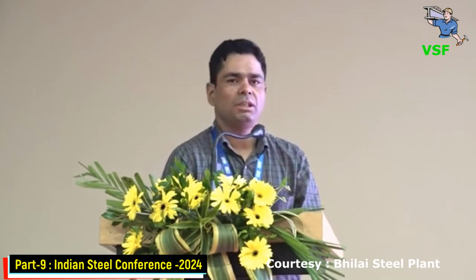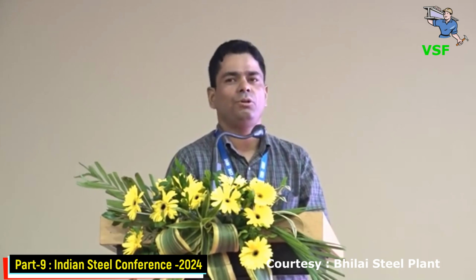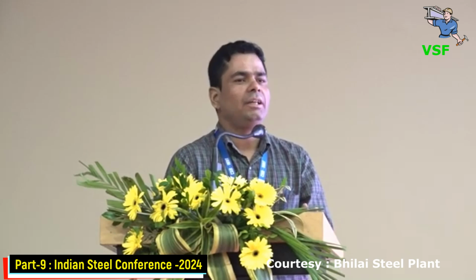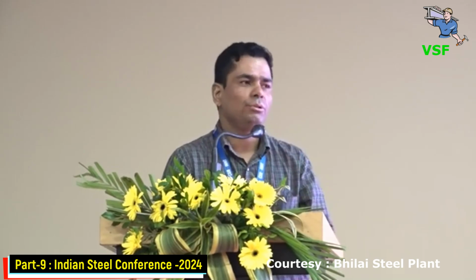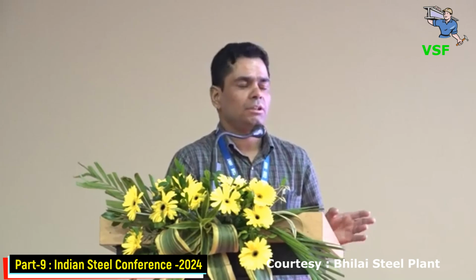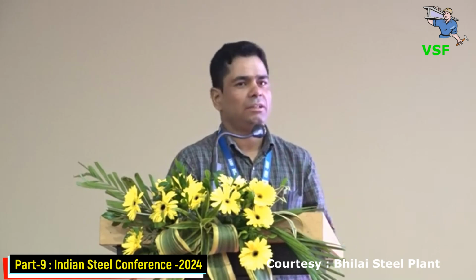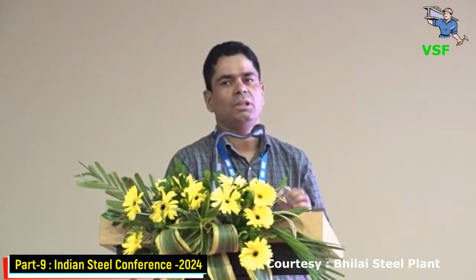But the problem is that with Indian low grade ores, we are having a significant amount of goethite, limonite and siderite, which are basically the hydrated and carbonated forms of iron ore, having the characteristics of clay kind of nature. Because of this, these low grade ores are not responding well to conventional mineral processing operations. These clay materials are creating flowability issues, and because of that, those instruments are not responding. Further, goethite and limonite are of soft characteristic, and hematite and the other primary ores are of hard characteristics. So because of which this is causing issues in the grinding.